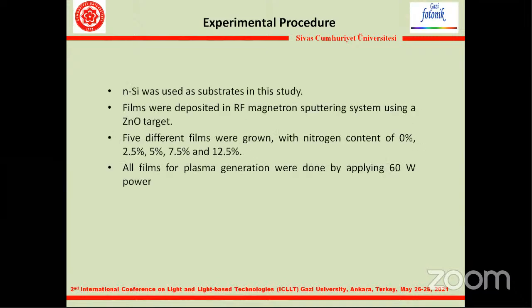Experimental procedure. In this study, N-type silicon was used as the substrate. Films were deposited in an RF magnetron sputtering system using a zinc oxide target. Five different films were grown with nitrogen content of 0%, 2.5%, 5%, 7.5%, and 12.5%. All films were produced by applying 60 watts of power for plasma generation.